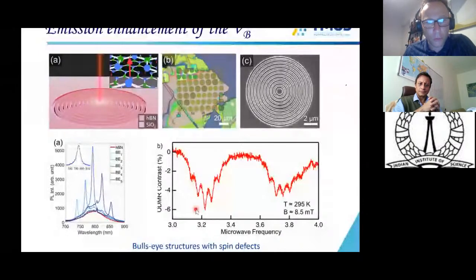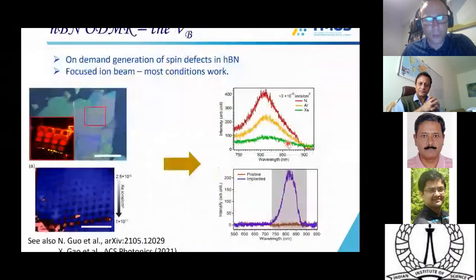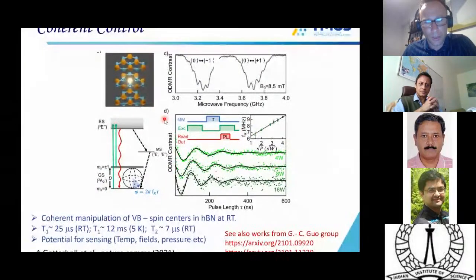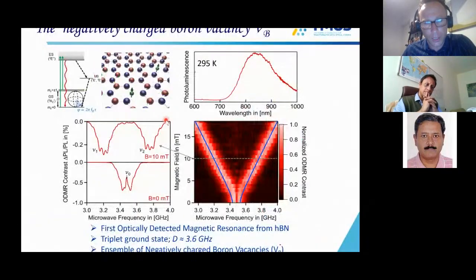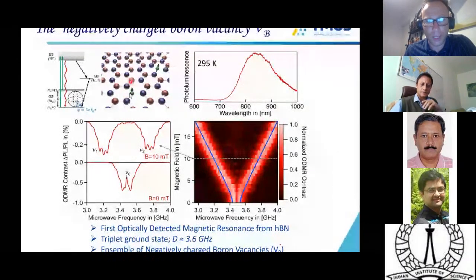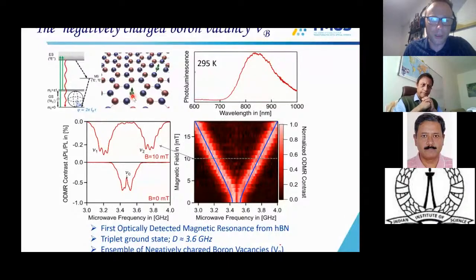But the boron vacancy, this defect, will actually never occur naturally. This is because the boron vacancy diffuses at very low temperature, about 200 degrees. So what you need to do is implant to create those boron vacancies, and then you do not need to anneal. You cannot anneal. If you anneal at about 800 degrees, this defect will actually break apart. So these defects you will not see naturally, but all the others you will.